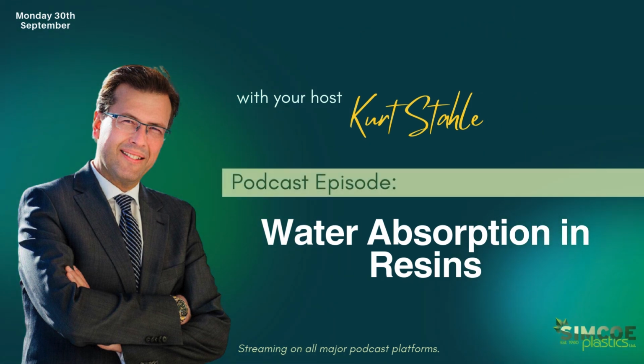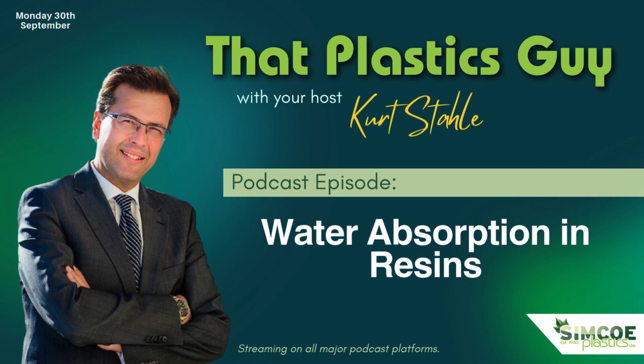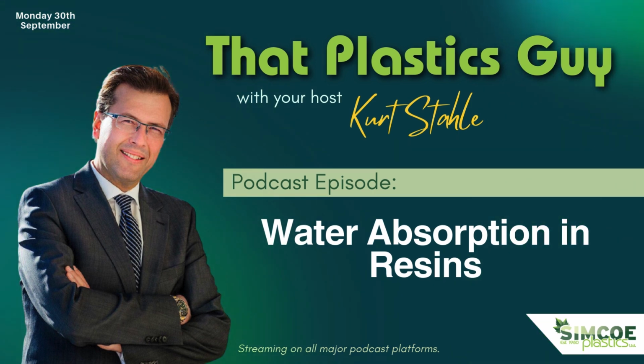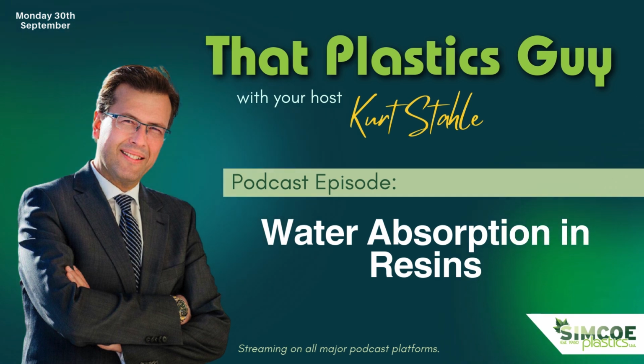And lastly, water absorption at equilibrium. The plastic specimen is exposed to a humid environment, typically at 50% relative humidity, at a specified temperature, room temperature, 23 Celsius, for 24 hours. The equilibrium moisture content can be used to compare the amount of water absorbed by different types of plastics when they are exposed to moisture. So we have a bit of a measuring bar there.